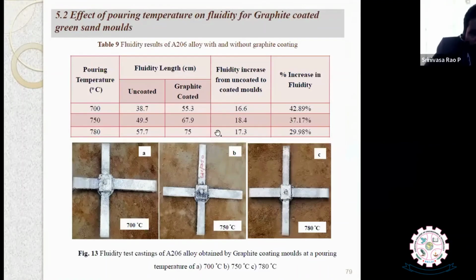So initially that, and after that we did experiments with graphite coated green sand molds also, for that optimized sand. Then we got the values for the three different temperatures, uncoated and graphite. See the difference, how much the fluidity increased by using the graphite coated sand mold. Okay, so this is the casting at 780 degrees centigrade. This is how the fluidity increased. We have compared uncoated and graphite.